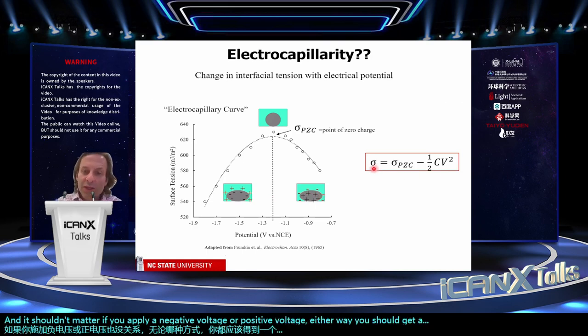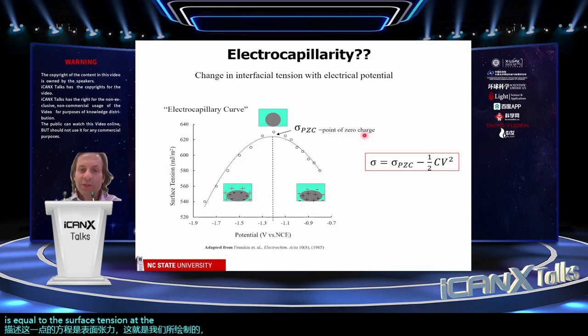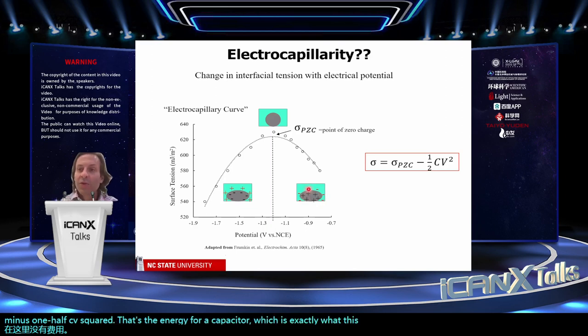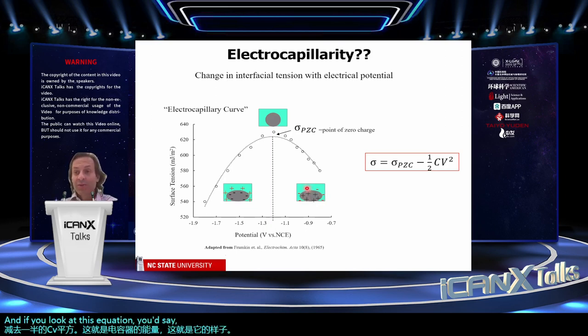The equation that describes this is the surface tension, which is what we're plotting, is equal to the surface tension at the point of zero charge. That's up here where there's no charge, minus 1/2 CV squared. That's the energy for a capacitor, which is exactly what this looks like. And if you look at this equation, you say, well, this is great. You just apply a big voltage and you can make the surface tension any value you want.